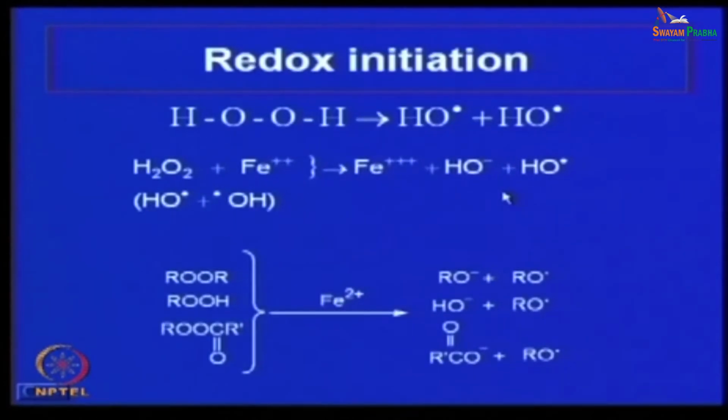That means from 0 to 50 degree Celsius temperature. At 0 to 50 degree Celsius, this redox system can occur, or say persulfate, potassium persulfate, ammonium persulfate. These can be used as oxidant instead of ferric. That is also a free radical polymerization.